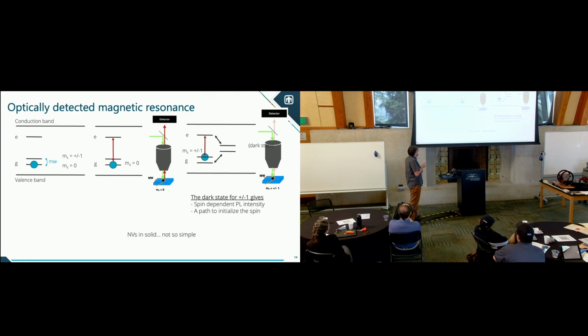But if you drive that into the plus or minus 1 state, there's a certain probability that it's not going to just go up and come back down. It'll actually go through a different side channel, a singlet state, and emit fewer photons into your detector. So in one case you have full light intensity coming out if it's ms equals 0, and if it's ms equals plus or minus 1, there's a contrast, a lower amount of photons coming out. And this is really nice from a quantum sensing perspective, because this dark state for the plus or minus 1 spin gives a spin-dependent photoluminescence intensity, so the amount of light that comes out depends on spin. But this decay path also returns it to ms equals 0. So it also gives you spin initialization. If you're optically pumping these NVs, they just tend to go to ms equals 0, and you have nice state initialization.